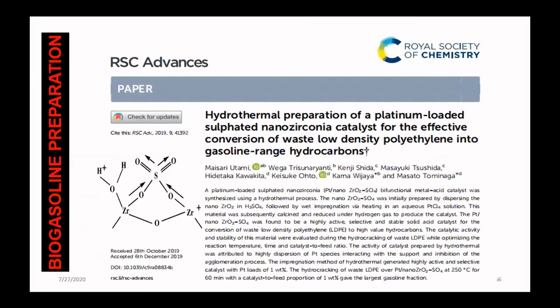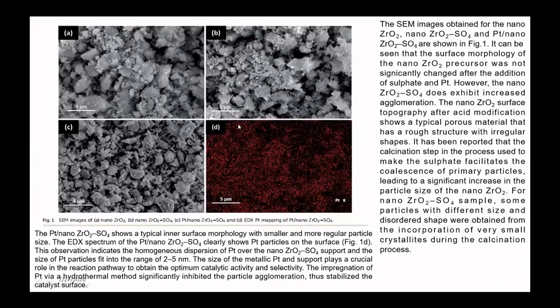Okay. Now we come to some examples of research that we have done in our laboratory: hydrothermal preparation of platinum-loaded sulfated zirconia catalyst for the effective conversion of low density polyethylene to gas and gasoline hydrocarbons. We use sulfated zirconia, and then platinum dispersed on these materials. We can see the dispersion is good using hydrothermal, and we obtain a relatively homogeneous material in this matrix.